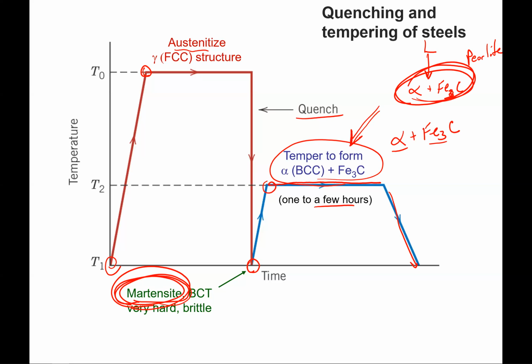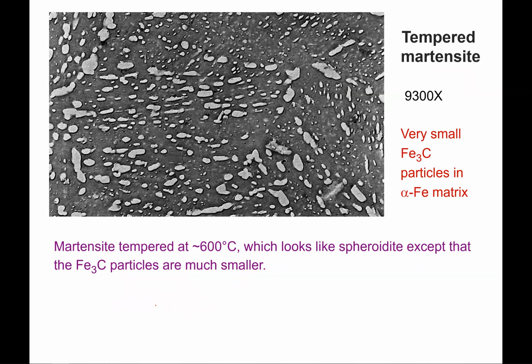And so we expect to have a very different structure, not a layered structure anymore like we had in the pearlite case. And in fact, what we get for tempered martensite, what it looks like is a matrix of ferrite with cementite particles all throughout. So this looks again like a composite material, but now we've got very small precipitates of cementite in this overall ferrite, which is a more ductile matrix.